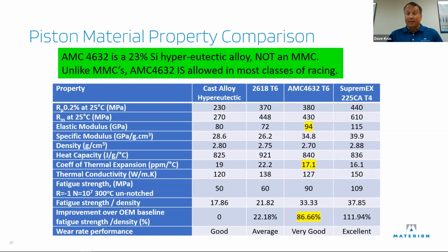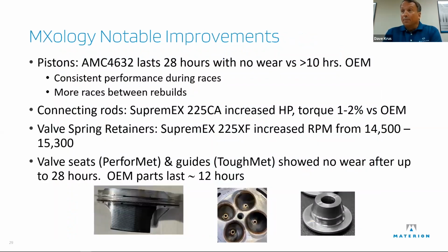So in comparison, the things that you'll notice make 4632 desirable is the stiffness. The elastic modulus is a lot higher than either the cast hyper-eutectic or the standard 2618 that you use. The coefficient of thermal expansion is lower than both, so you can have a tighter starting clearance. Again, it's not to where Supremex is, but it offers you better machinability than the Supremex. And the fatigue strength over density is nearly double of what the cast hyper-eutectic has, and about 50% more than the 2618. So it's a very, very good piston alloy. It's not quite Supremex.